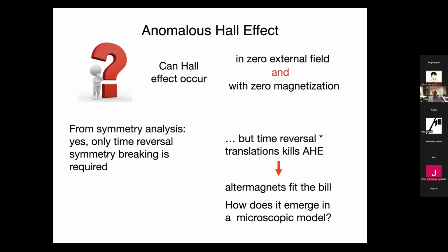The only thing that's required is time reversal symmetry breaking. However, if you look a little bit deeper, time reversal times translation kills the anomalous Hall effect. And that's interesting because that's exactly the symmetry that altermagnets do not have. And indeed, altermagnets fit the symmetry bill to have an anomalous Hall effect. And the question we ask ourselves, that's great if it's symmetry allowed, but can we define a microscopic model in which this altermagnetic Hall effect indeed occurs?